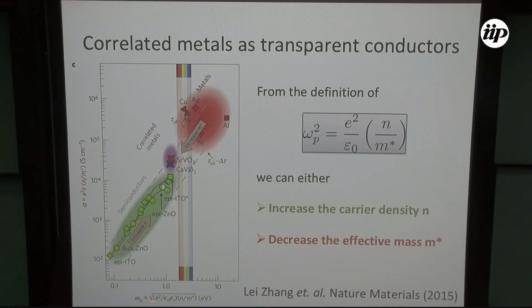What's plotted here is the plasmon frequency, and here is the conductivity. So you want good conductors. That's why you are heavily doping semiconductors. You are trying to increase N. That's why it's in green here. So we are going up, but you cannot go too much to the right, because otherwise the plasmon frequency will enter the visible and you don't get what you want. So these guys here published a paper in 2015 where they tried the other approach. Let's start with metal, and from metals, let's start adding strong correlations, because in this way you increase the effective mass.